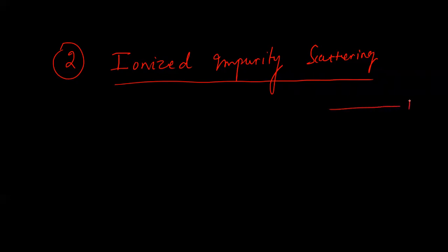So we said you have the conduction band over here and the valence band over here. When you add a pentavalent impurity, it will create a donor energy level over here, ED. These donor electrons are loosely bound in the donor energy level, and the energy required is of the order of 0.01 electron volt. We have already discussed what ionization energy is in some other video; you can refer to that.